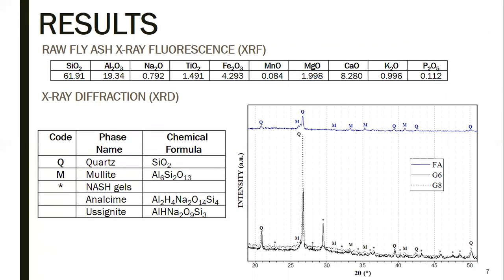Results. X-ray fluorescence of raw fly ash shows that the main content of this material is silicon and aluminum, which makes it a great aluminosilicate source in the geopolymerization process. The X-ray diffraction shows that the main peaks of fly ash are quartz and mullite. These phases also appear in both geopolymers, but we can see that geopolymers got more new amorphous phases like analcime and ussignite, which makes the geopolymers more porous.